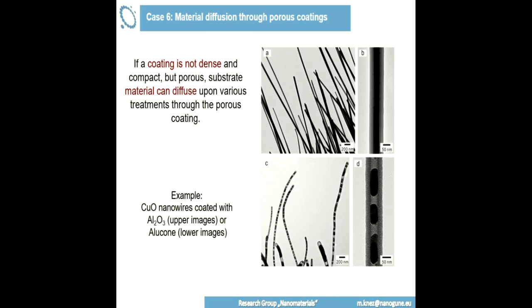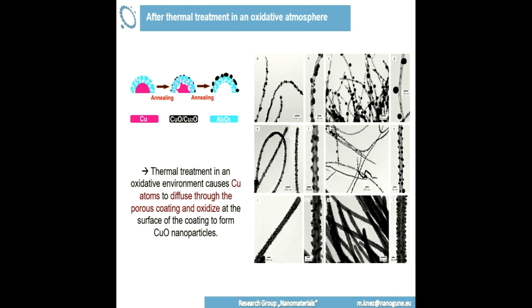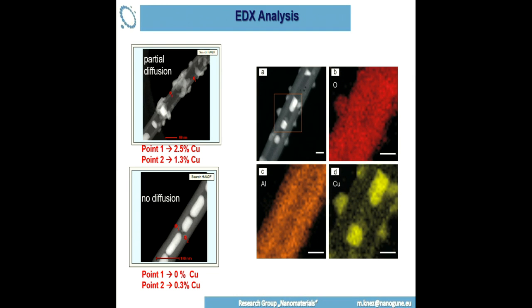And this coating is less dense, and it's pretty much permeable, not only for gases coming in, but if you heat up such a structure, what can easily happen is that the material inside can migrate to the outside. It means those coatings are already so permeable that even material transport can happen. In this case, copper diffused through these porous coatings to the outside and precipitated there. It was very obvious that this happens. And you can even see it, for example, on EDX scans. Here, this is the copper inside of this shell, so it's not copper migrating around, it's going through the coatings. So the more porous and the less dense your coatings become, the more possibilities of permeation, diffusion of either gas molecules or even materials you have.